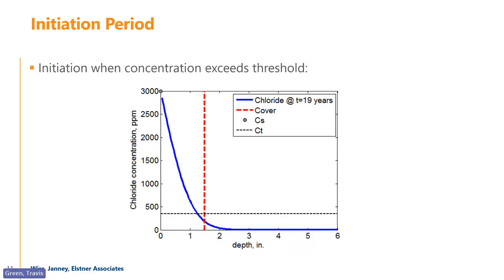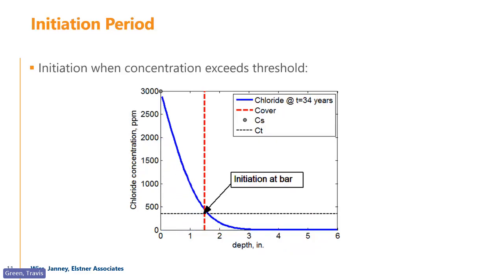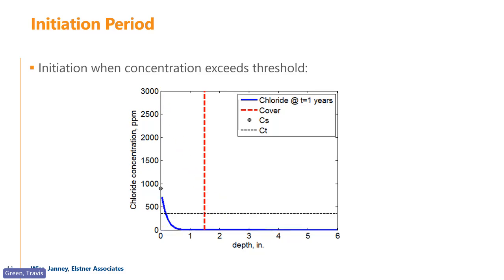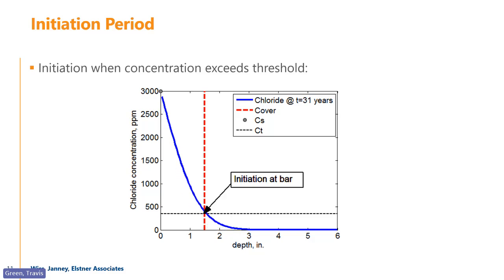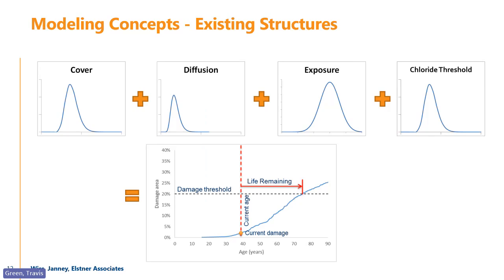So this graphic shows, kind of interactively, right, that we're increasing chlorides at the surface. And then they start to diffuse, and they get more and more as they get deeper into the concrete, and eventually, if we have a bar at 1.5 inches, we have chlorides over a threshold, which we would say starts the corrosion process at that bar, right? That bar is no longer passivated, right? So just another kind of graphic there.